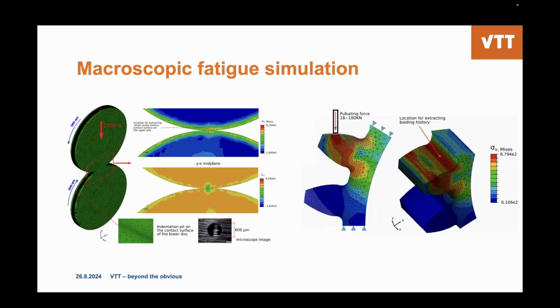We have also made an indentation pit at the lower disc as we have used in experimental work. And on the right side, to simplify the simulation, we only model the two teeth with a pulsating force from 18 to 180 kilonewton. And the location for extracting loading history is here for the gear root, and here, one element below the surface of the twin disc.